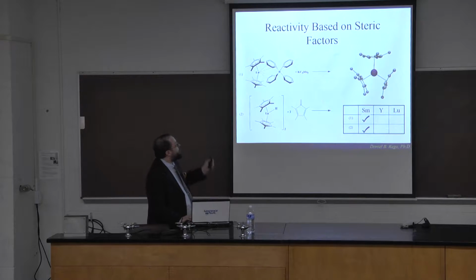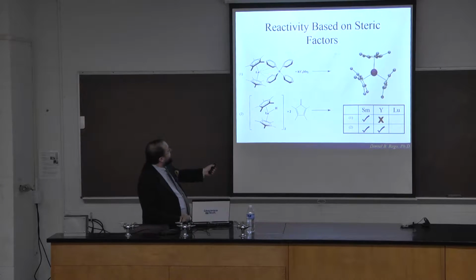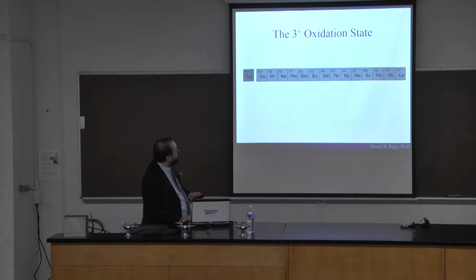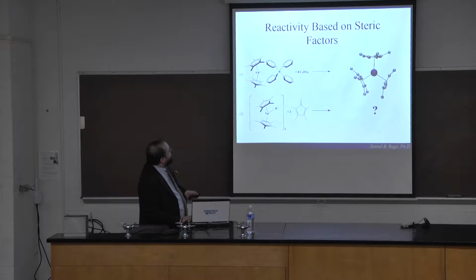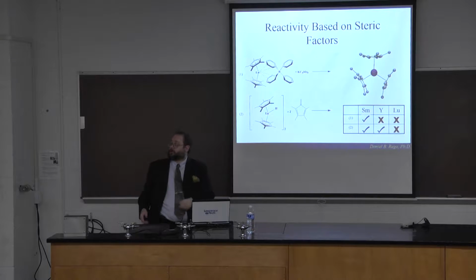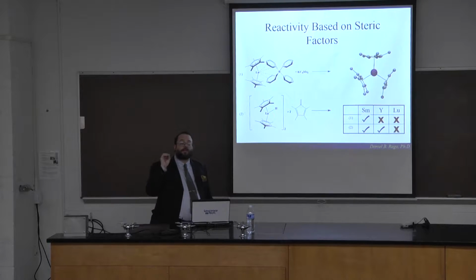For the relatively large samarium, both of these methods work perfectly fine. When you get to something the size of lutetium, basically this doesn't really work. This is just too sterically hindered, so this won't form. But this method kind of forces it to, so you can get the lutetium compound through that method. Lutetium, which is the smallest of the lanthanides, it just won't work with the other. It's just too crowded, there's just not enough room. So that slight change in ionic radii completely changes the reactivity.